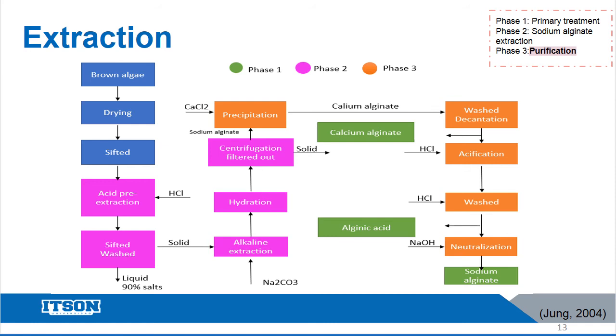This allows absorbed water to be removed. Finally, sodium alginate is obtained from the acidic solution of the alginic acid by alkalinization with caustic soda. As this alginate is soluble in water, it is dried in a vacuum oven at 50 degrees until constant weight.